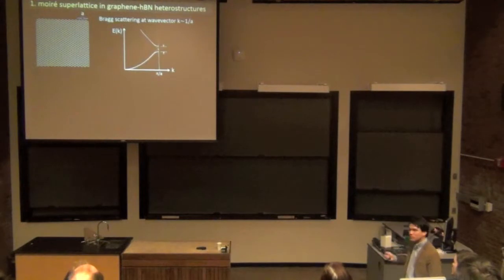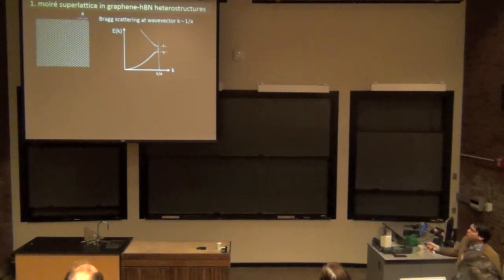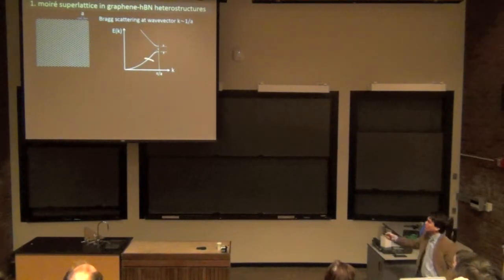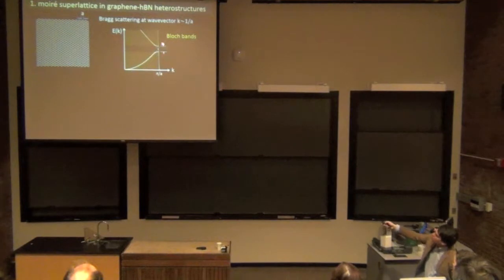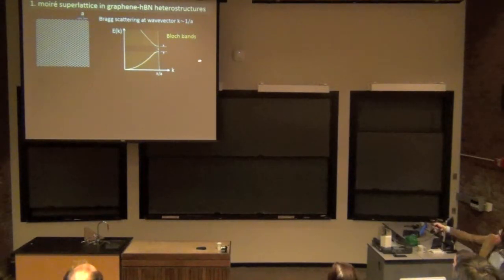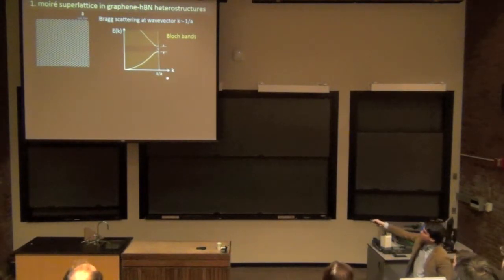So if you go back to elementary solid state physics, look in Ashcroft and Mermin, what you find is that when you have a periodic structure, the normal free electron behavior of electrons gets modified when you get close to momenta that are proportional to 1 over the lattice parameter. And what you get there is a reconstruction into so-called Bloch bands. You basically get what's called Bloch or Bragg scattering at these wave vectors. And the free electron dispersion breaks up into these so-called Bloch bands. And this happens at relatively high energy because this a here, which is just the lattice parameter, is relatively small. And so this is at high momenta and high energy.